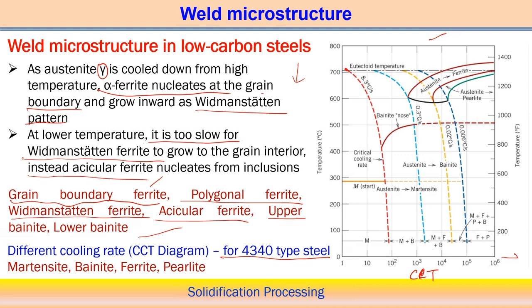And if you see the x axis, the time frame is given, and the y axis is basically temperature here. So it starts transforming from this particular zone, above 700 degrees centigrade or so. It is gradually cooling, but we follow a certain cooling rate, say 8.3 degrees centigrade per second. This is the cooling rate. It follows one particular structure.